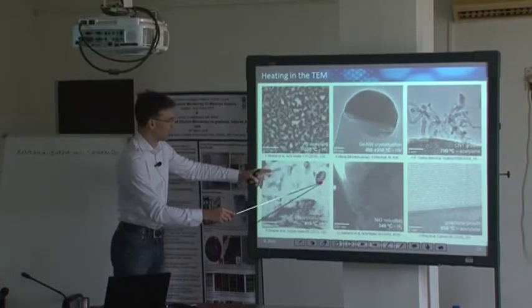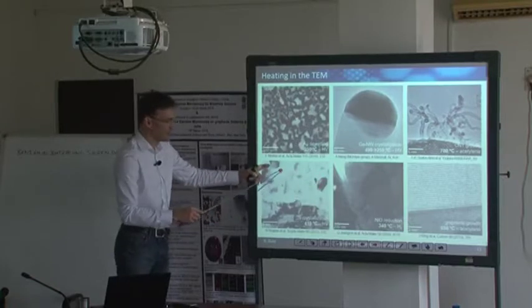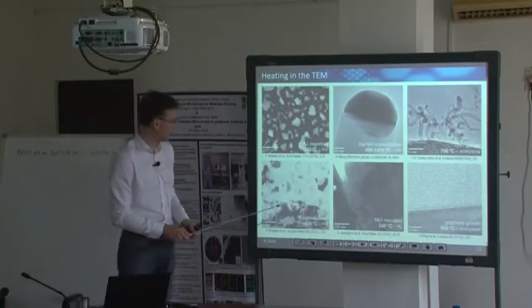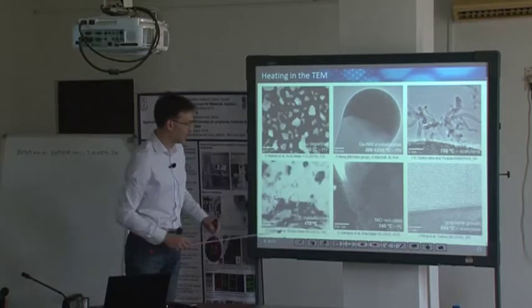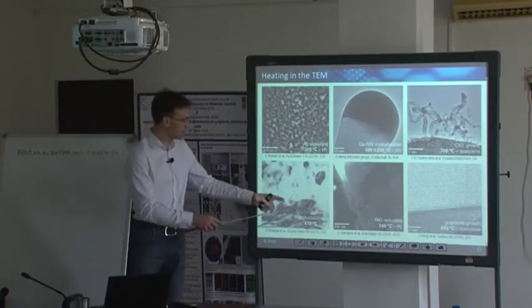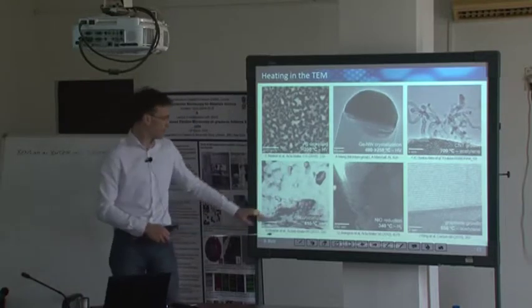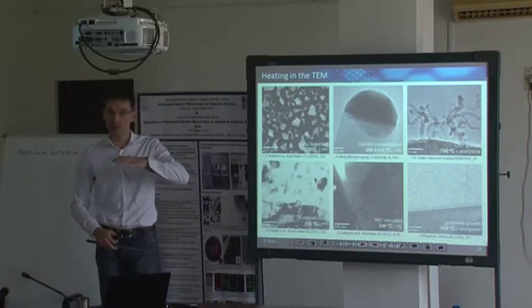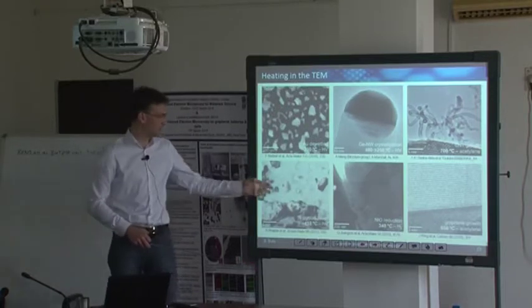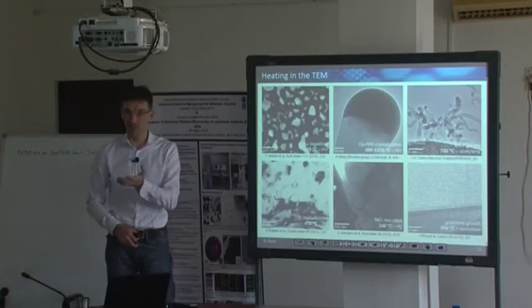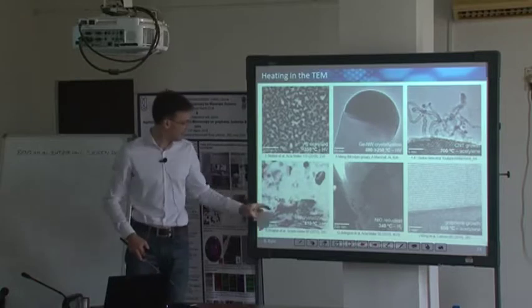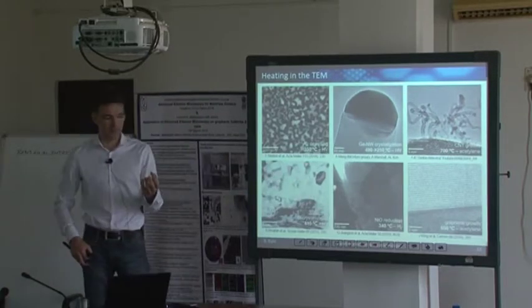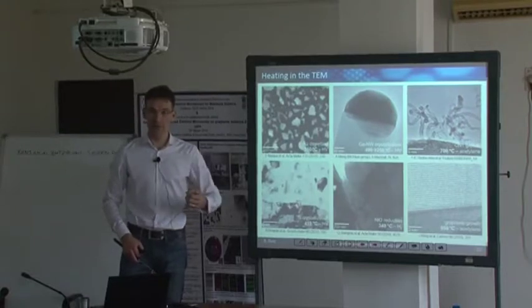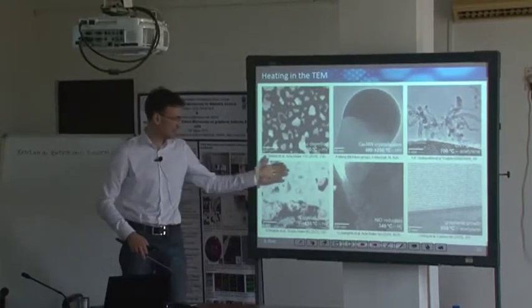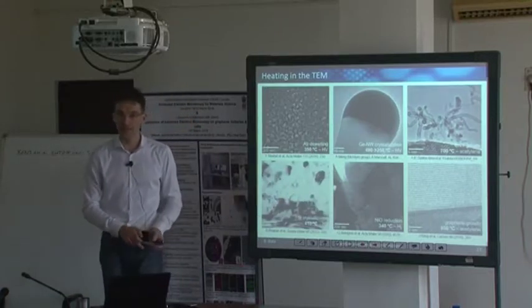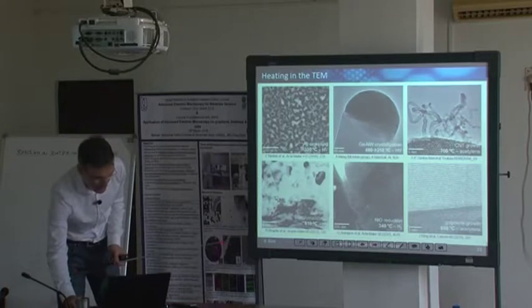You see these bent contours and some diffraction contrast. This is the aluminum film that Balaji may utilize for this AIC process. And this is already the crystallized silicon layer. In this particular case, the question came up how the aluminum from this lower layer is transported into the upper layer through this diffusion barrier that was deposited as well. And it turned out that in some areas, which you hardly see here, this diffusion barrier layer just breaks, and you have a very rapid push-up of the silicon because there is some stress involved. Stress occurs, and that causes the failure of this interlayer.